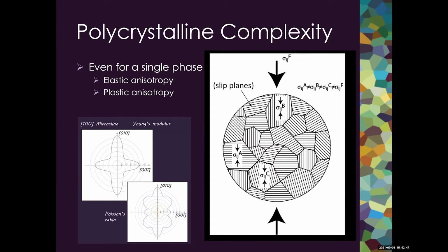Polycrystals are elastically anisotropic and they're also plastically anisotropic. This top left-hand figure here just shows a diagram for the anisotropy of the Young's modulus for single crystal microcline. And this just shows us that depending on the crystal orientation, the elastic modulus will have a different value. And so even for a single phase aggregate under deformation, things can become complicated. And when you introduce more than one mineral phase, there's an increased level of heterogeneity, which leads to more complexity.